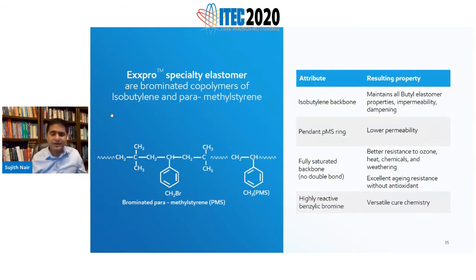It basically is very resistant to heat and ozone, just because there is no point to cleave this. It maintains all the advantages of the butyl material, but it also gives some other advantages. So the pendant PMS ring, so you got this bulky PMS group there. Two things that it does is it actually reduces your free volume, and it also reduces your segmental mobility. So what does that mean, right? Reduction in free volume means an increase in Tg, and basically that's how you get your lower permeability.